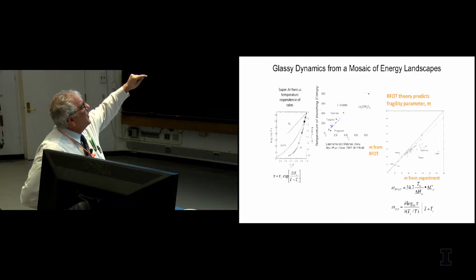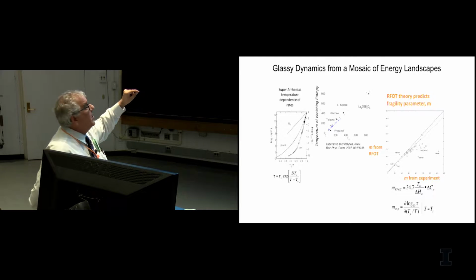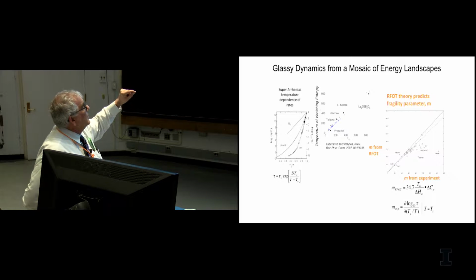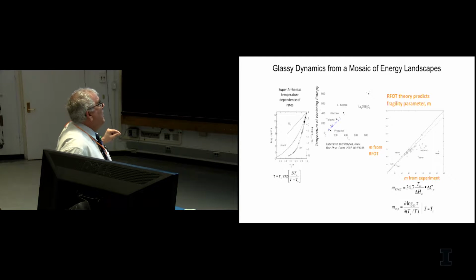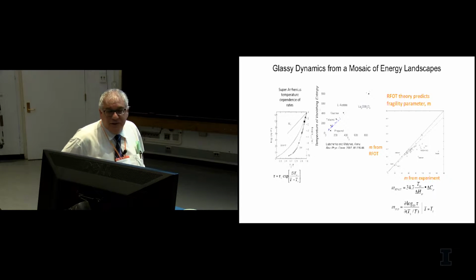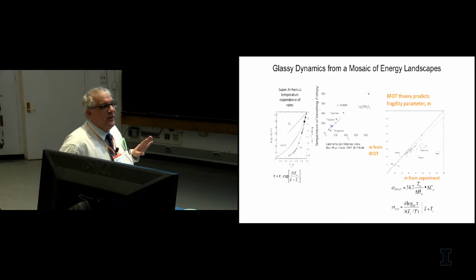we just had to actually make a plot. And that's a plot of the T0s determined by purely thermodynamic measurements, the temperature of vanishing entropy determined by purely thermodynamic measurements, and this T0 in this fitting form. And you can see they lie not just in a correlated way, that's the line with slope 1. People always argue about this because they say, oh, it involves an extrapolation.